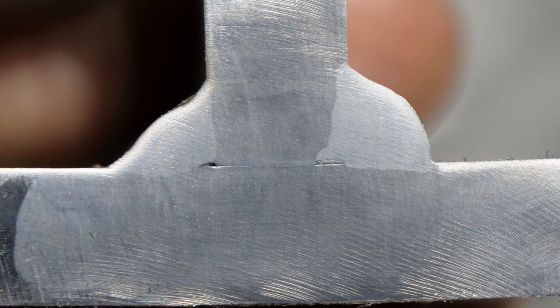So guess what? It bit into the sides. However, the root is not looking that good. It's kind of odd that it melted the upright plate, you can see that back past the root, but it didn't fuse that into the bottom plate. The settings that I was running for this flux core wire were a little bit on the low side, which is why I did a third test.